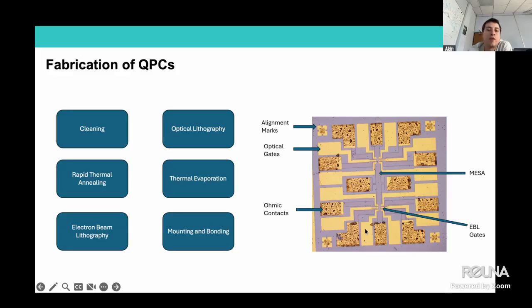Then there will be optical lithography to build these larger patterns to deposit certain materials like gold or alloys. Of course, there's an order that matters for this, because there are ohmic contacts which need to be annealed into the structure so that you can make a contact from the top and then reach the two-dimensional electron gas to inject the electrons.